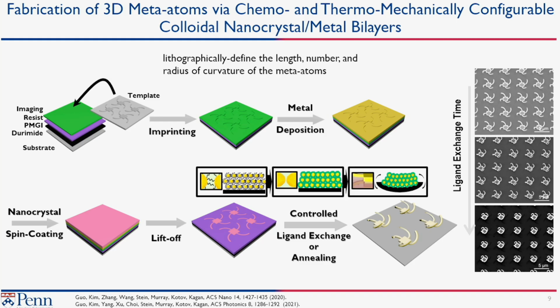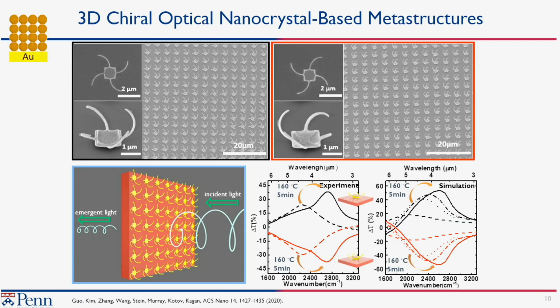So what you can see here, just as an example, is that if we take the same sample, just make multiple samples, we can do this over and over again. And we just control the time of the ligand exchange, right? That's going to control how well we bring the nanocrystals closer together. You can see that we can control the folding of these structures. And now we've done this for many years in different materials, and we've gotten fairly well practiced at this. Okay, so this is where we started.